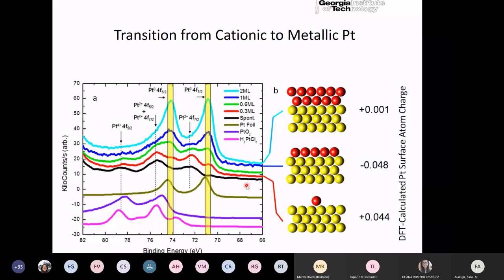So, for example, you wouldn't know that when it's one layer thick, it prefers to be 100, versus when it's 3 layers thick, it prefers to be 111. For that level of information, you need spatial resolution and an imaging ability. So I would say that TEM is probably the best way.